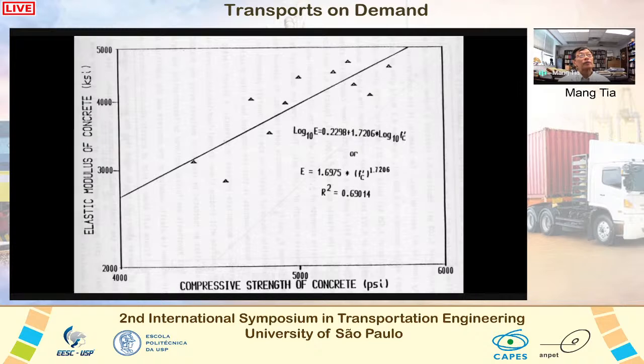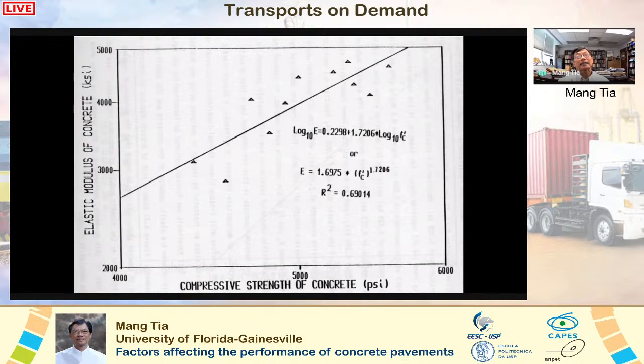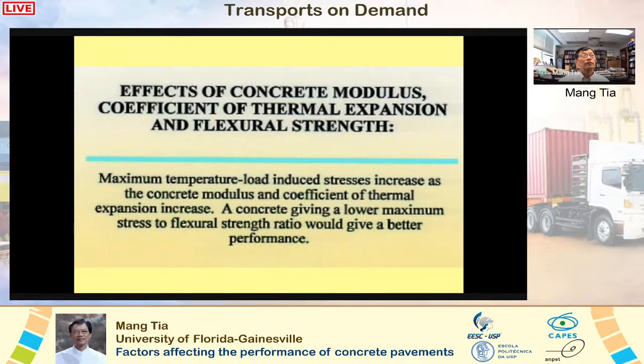Usually, concrete with higher strength is accompanied by higher elastic modulus, as shown in this plot of elastic modulus versus compressive strength of concrete. Thus, using a stronger concrete may not necessarily give us better performance, as the performance of the concrete pavement is also affected by the elastic modulus and coefficient of thermal expansion of the concrete as well. We can say that maximum temperature-load induced stresses increase as the concrete modulus and coefficient of thermal expansion increase.